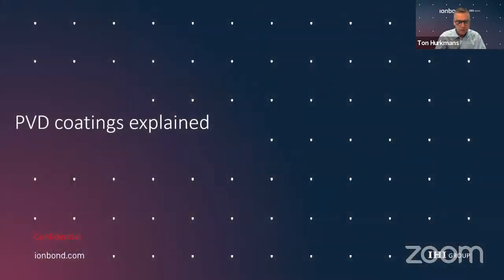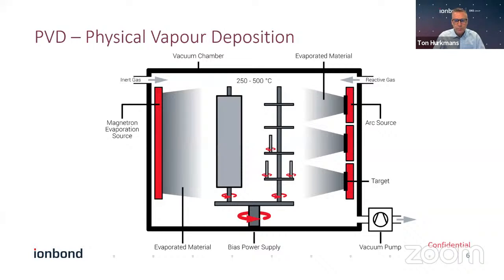A short word on PVD and PACVD coatings, if you're not familiar with this. PVD stands for physical vapor deposition. We have parts on a carrier in a machine, and it's a vacuum coating machine. In order to create a vacuum, we have vacuum pumps to get that state. Then we have defined gases coming in, symbolically on the top over here. What we actually do is evaporate metals into a metal flux. You see it here on the right in this cone, for a so-called arc evaporator, and it sprays on the parts, and we form a coating because the metal flux will condense on the surface of a part.